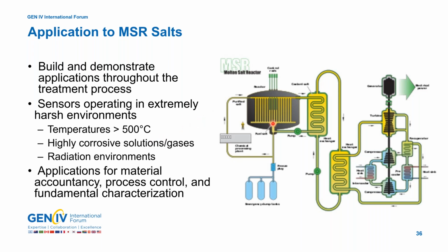In one case, we're looking at the uranium and the fuel salt, and this is a schematic of one of the Gen 4 type reactors where we have molten salt fuel that's circulating through the reactor. And the idea is to put a probe in to measure the concentration of uranium in the fuel salt. And also we're concerned about off gases coming in from fission products. And so we want to design probes that can measure both the salt at temperature. So we have high temperature sensors that we're designing, and also sensors that work in the highly corrosive solution, the molten salt solutions, and also in the gas system.